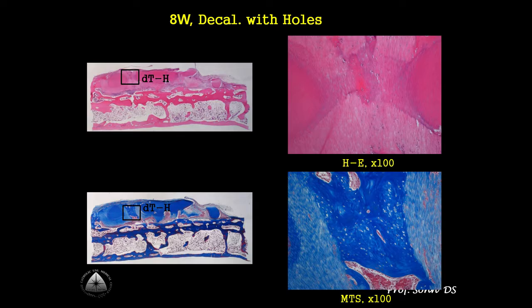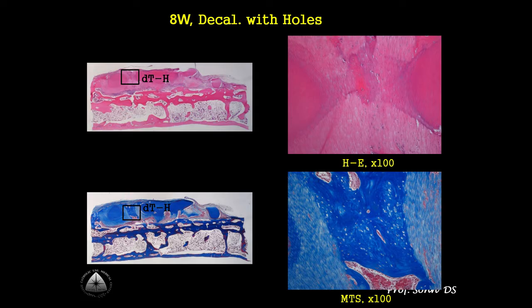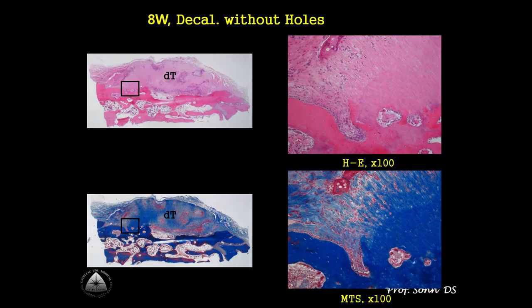At 8 weeks healing in Group 1, new bone formation and fibrovascular tissue were well attached to the dentin bottom and micro holes. In some areas at the bottom, replacement resorption of dentin was observed. New reformed bone and osteoblasts were observed at the calvarial and dentin contact surface, and osteoclasts were found at the dentin surface — indication of bone remodeling. Group 2 showed good bone regeneration at the junction of dentin block and calvaria.